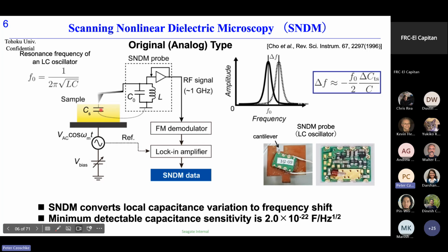And by the application of the bias voltage, tip-sample capacitance is modulated, in dielectrics due to the nonlinear effect, and in semiconductors due to the modulation of the depletion layer. So the tip-sample capacitance is modulated, then the oscillating frequency is modulated. As a result, a frequency modulation signal comes from this SNDM probe, whose frequency deviation is proportional to the capacitance variation occurring under the tip. And by using an analog FM demodulator, we can convert the frequency deviation, or capacitance variation, to a voltage signal. And using a lock-in amplifier, we can obtain the dC/dV signal as the SNDM data.